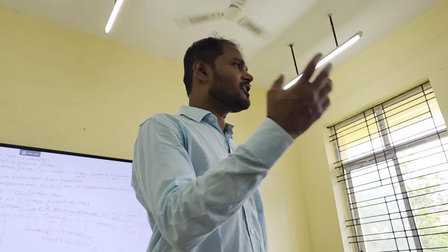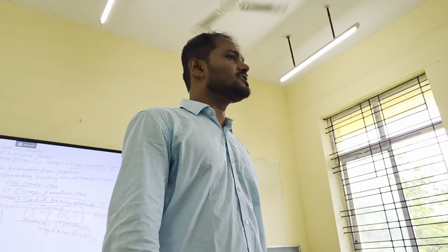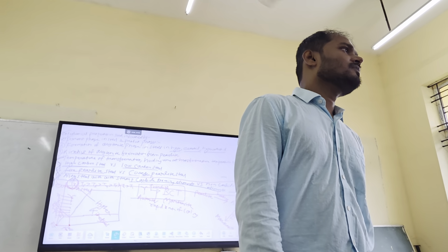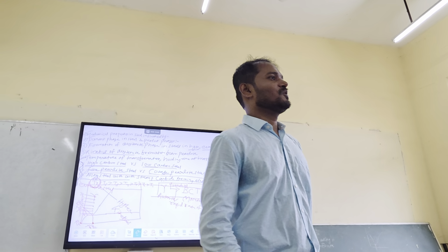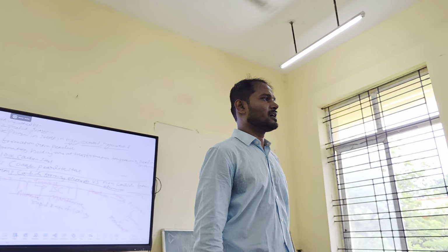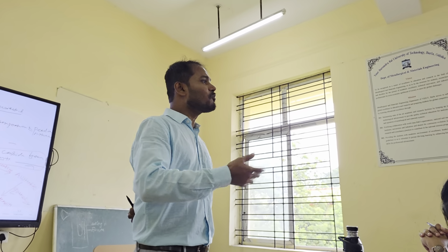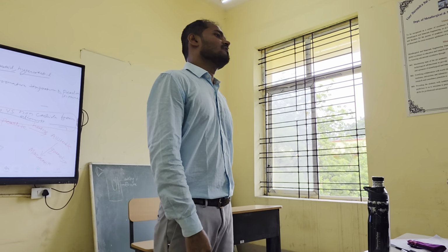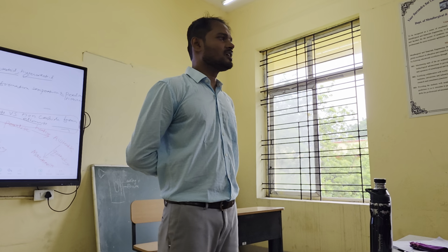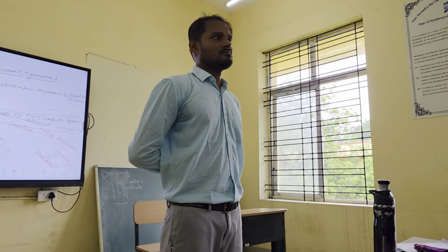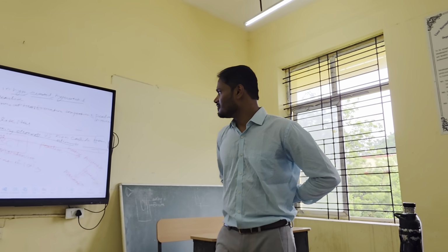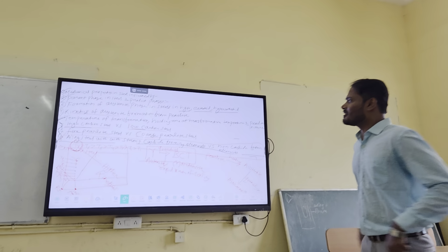Fine carbides means a lot of carbides, a lot of interaction between the dislocations and the carbides. Dislocations cannot move easily, and they need to shear the carbides also. That is the shear mechanism. To do shear, you need more energy. More energy means you need to provide more tensile stress. Obviously, strength will be more. These are the concepts. Okay, we are done now. So these are very important.